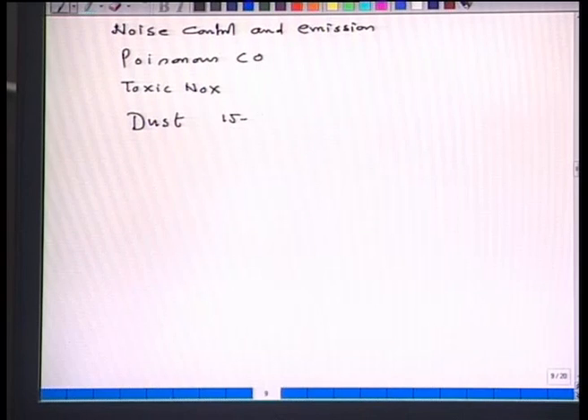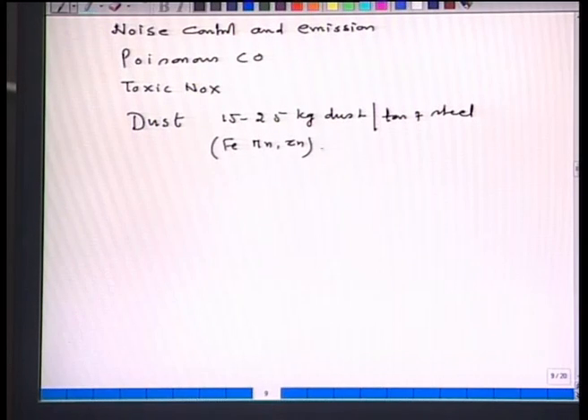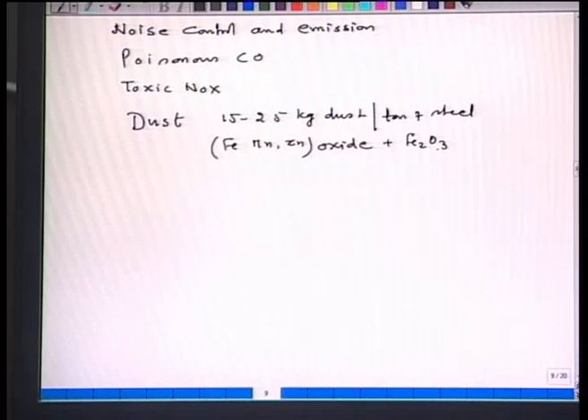Around 15 to 25 kg dust is produced per ton of steel. Now, this dust contains iron oxide, manganese oxide and zinc oxide. From where is the zinc coming? Zinc is coming from the automotive scrap, because if galvanized steel scrap is being used, then a large amount of zinc will also join the dust coming out of the electric arc furnace. It may also contain Fe2O3, which is a highly oxidized state of iron, may also contain FeO, may also contain SiO2, because all these things are generated because of the very high temperature in the electric arc furnace.